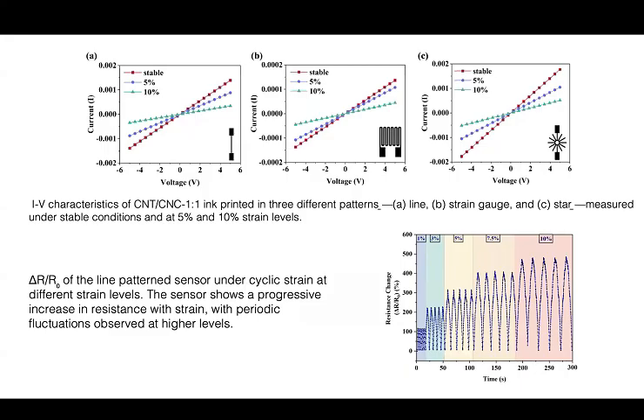So what is the common practice? You basically check the IV curve, whether it gives you enough electrical response. But at the same time, you also need to monitor the resistance under cyclic strain levels, and understand and map the response of the different strain levels to the increase of resistivity with strain, because it is going to change. So why is this quite important for us?